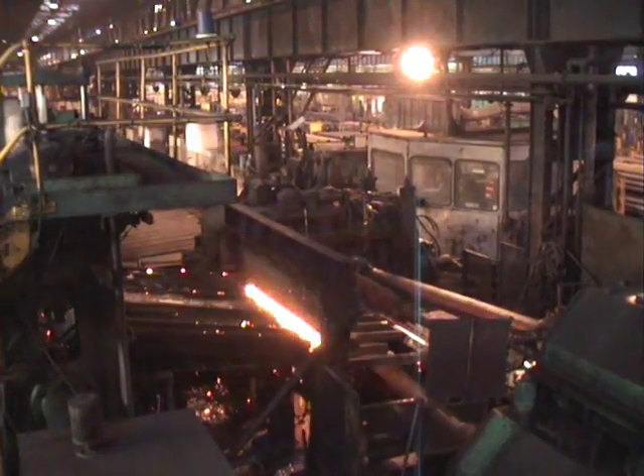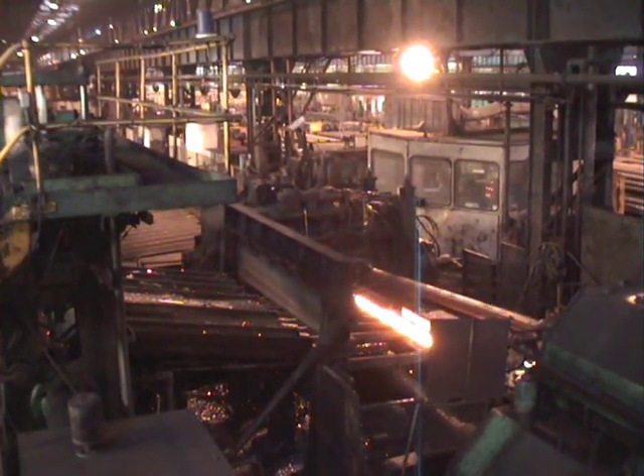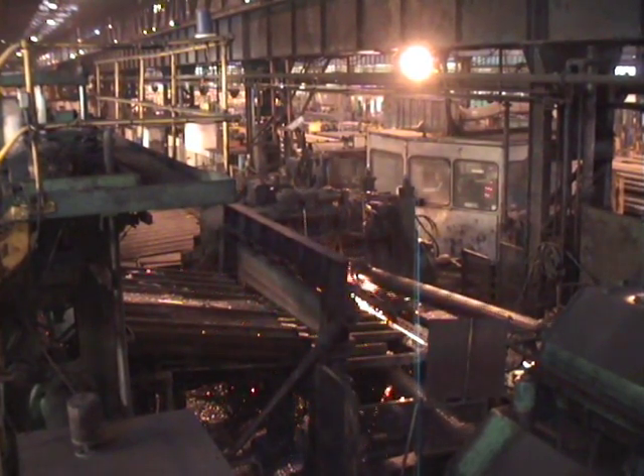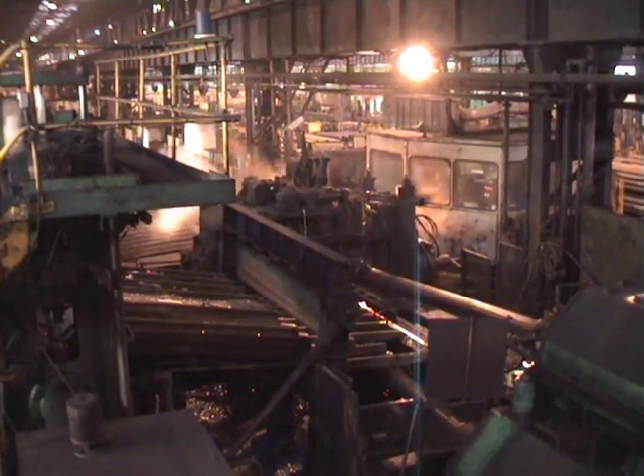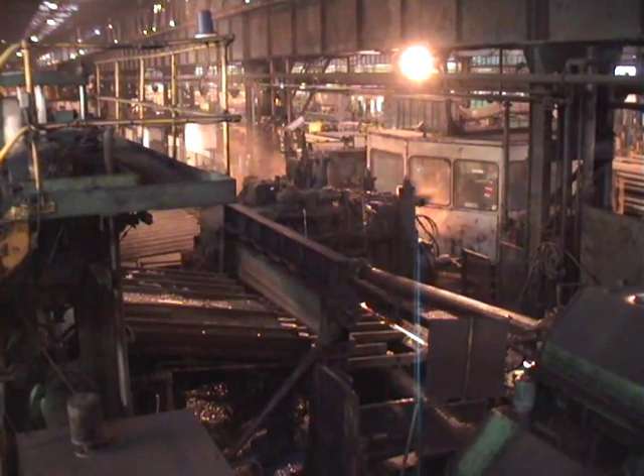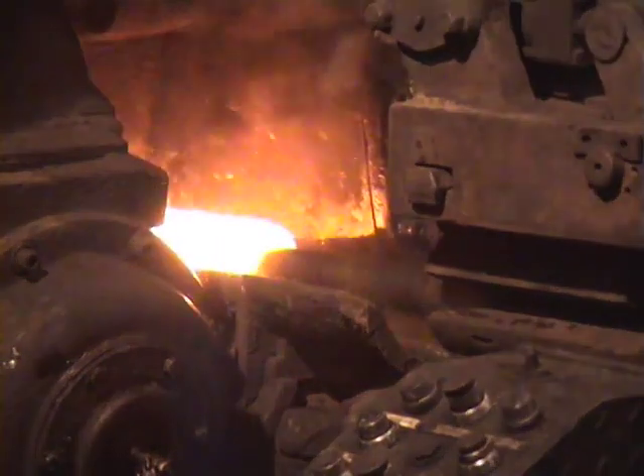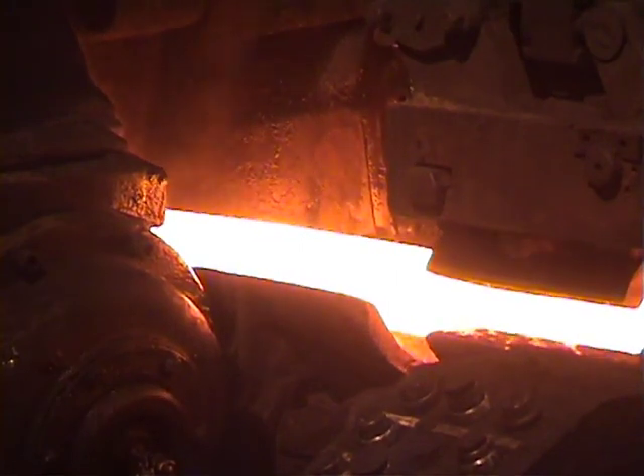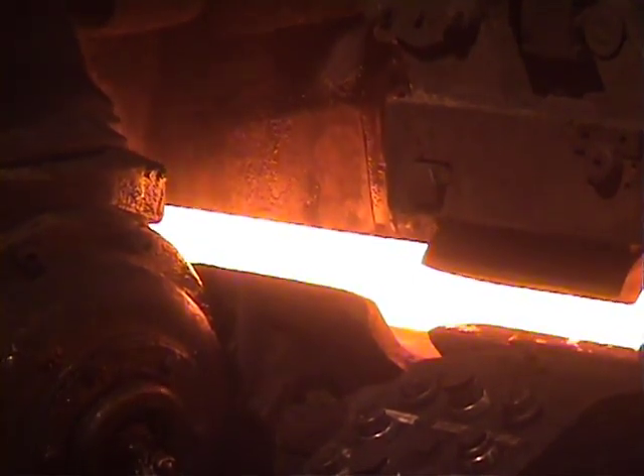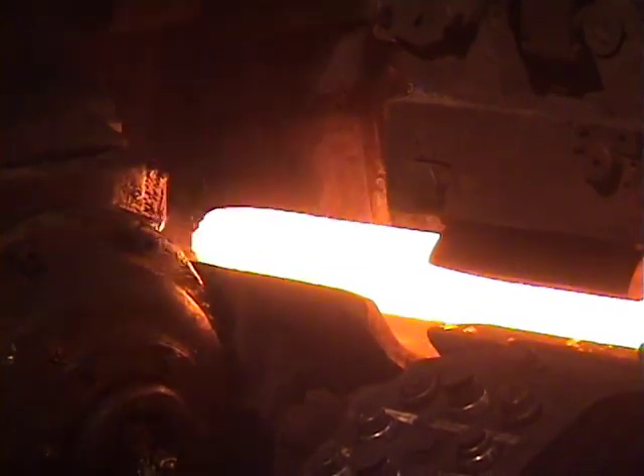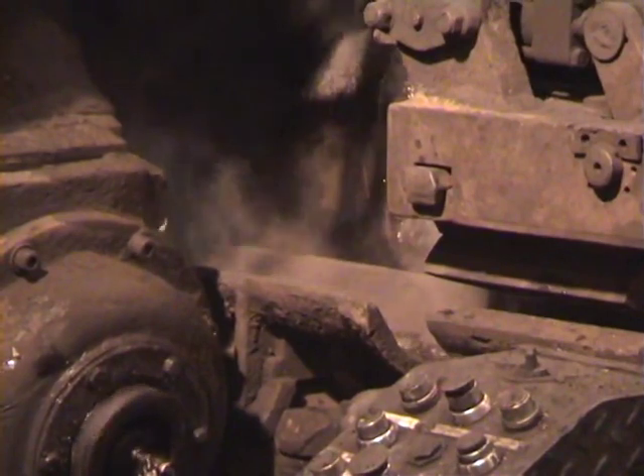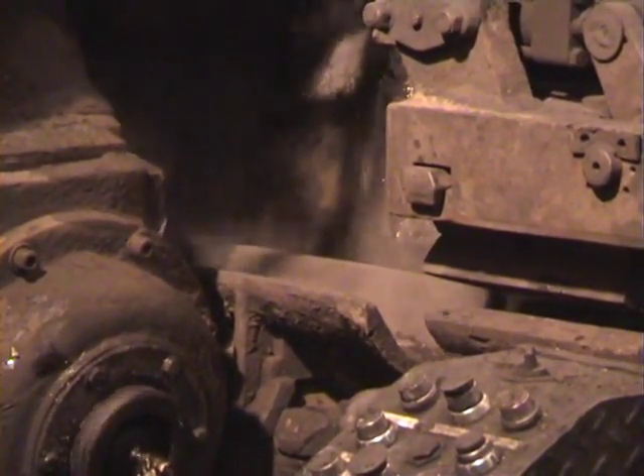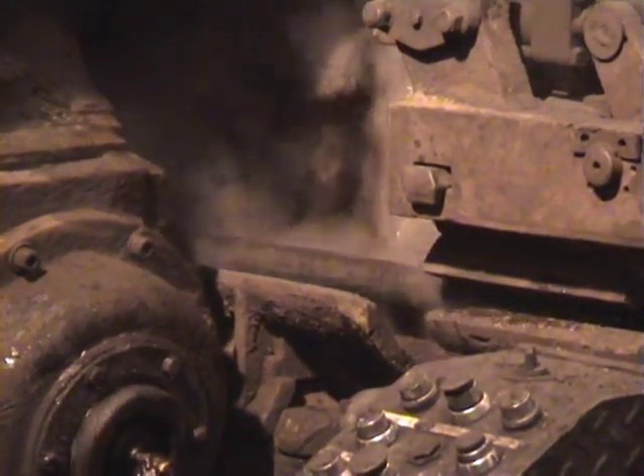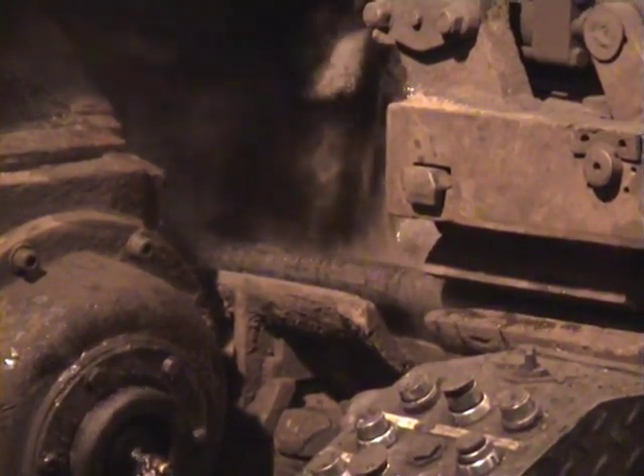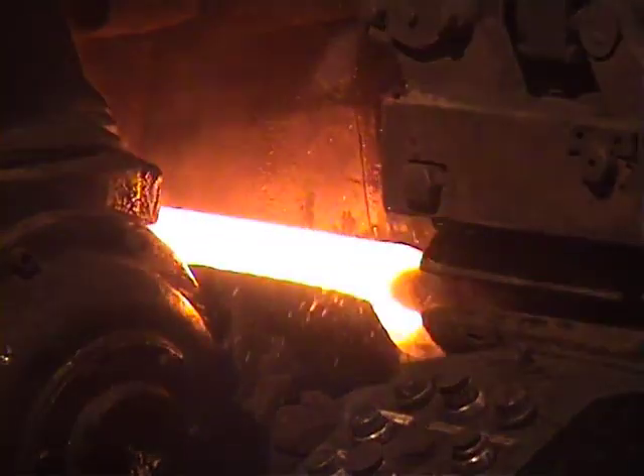The billet rolls down to the inlet of the piercer, where a hydraulic ram pushes it into the piercer roll. The 2 barrel-shaped rolls of this mill are inclined at an angle to feed the billet into the mill. They are driven by a 2,000 horsepower DC motor, geared down to give a roll speed of around 150 revs per minute. The stresses created in the centre of the billet allow it to be fed over a conical steel plug, which is positioned at a critical point between the two rolls. This creates a tubular shell known as a bloom.